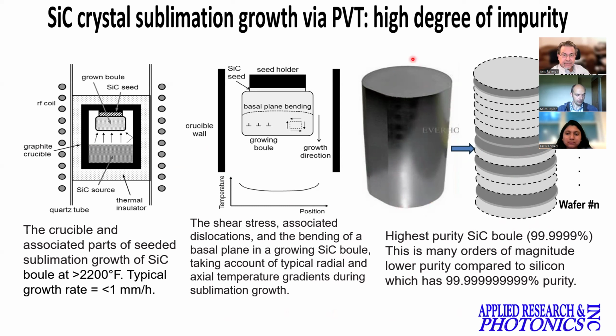So what happens in the case of silicon carbide is that this boule length is very short. In silicon, it can be a 2-3 meter long ingot. If an ingot is 2 meters long, how many wafers can we get out of that? Quite a few, right? If each wafer is 1 millimeter thick, for example, then you get 2000, but wafers are less than that. So per meter of boule, you get 1,000 or more wafers from silicon.